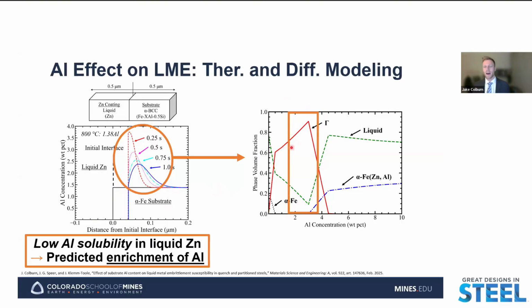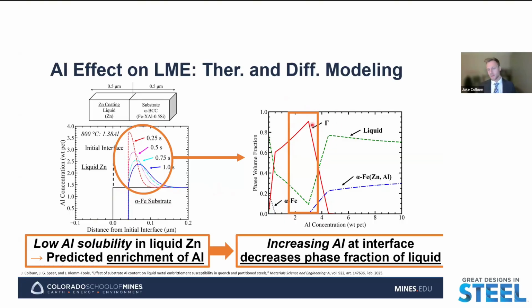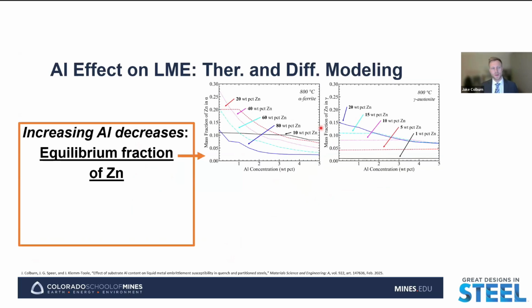So we would expect that with that interfacial composition the gamma phase would be stable. And so we would say that that is potentially going to be beneficial for LME susceptibility, again decreasing the availability and presence of the liquid phase by having more of the gamma phase present. But then we can also take a look at how the change in the substrate aluminum concentration is going to affect the diffusion of zinc into the substrate or affect the solubility of zinc in the substrate.